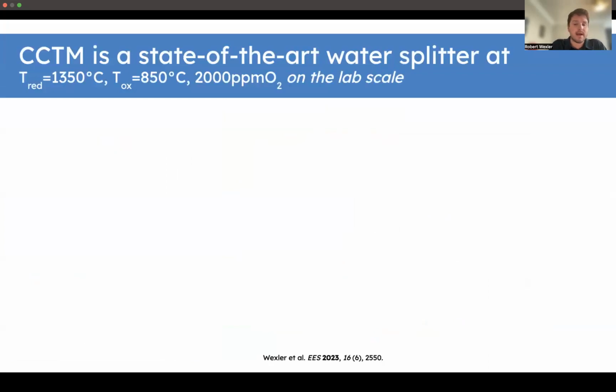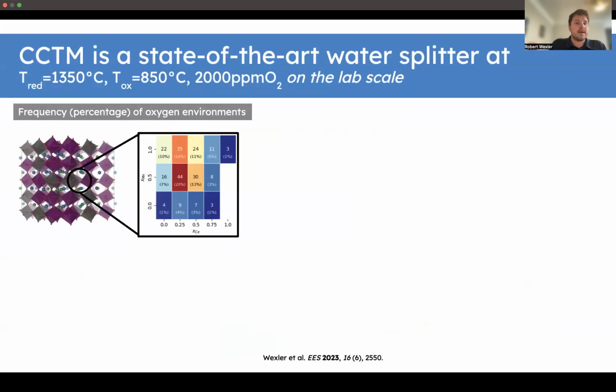Okay. So now, having shown that our prediction manifested as a stable material that could be synthesized and was characterized using XRD, we then went on to show theoretically that it could actually split water. And for us, that means calculating the neutral oxygen vacancy formation energy. But to do that, because we have a quasi-random structure, we had to consider a finite number of possible oxygen environments. So here I'm showing the crystal structure and focusing in on the frequency or percentage of different types of environments that could be present in the crystal.